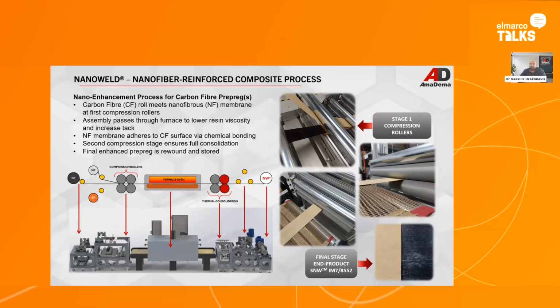This is quite non-trivial, because nanofibers are very porous. We can achieve the desired permeability, but the pore size is a tricky point that can block, let's say, the resin flow during the prepreg. So this needed from our side a lot of work and a lot of experimentation in order to find the appropriate resin systems that would be able to go through the nanofiber and basically wet very well the carbon fiber bed or other types of fibers, similarly to prepregs that do not have nanofibers.